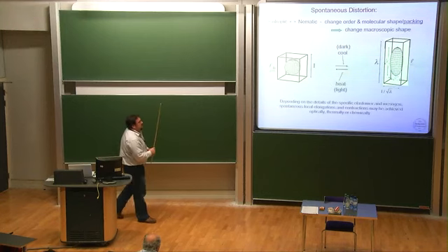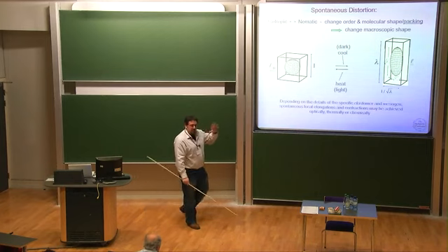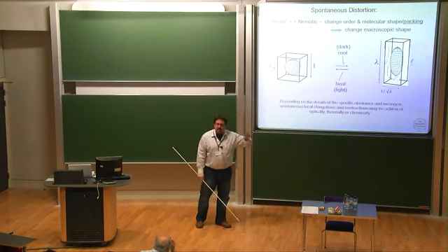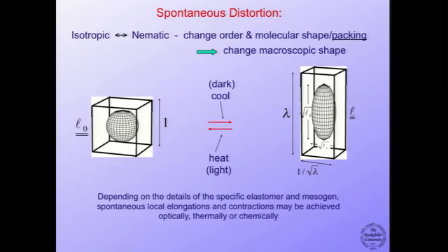So why are these possibly interesting? We've heard about this before, but because it's so important to the effects, I want to give you a quick refresher. Upon change of the nematic order parameter, you change the degree to which those polymers are lined up along the nematic, and so you change the amount by which the statistics of the random walks are changed. You change that bias, and by changing that bias, you change the length scales.